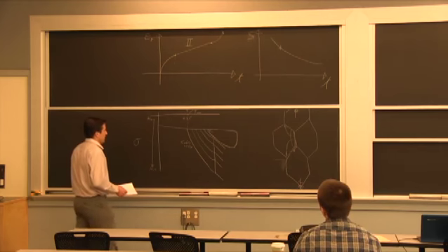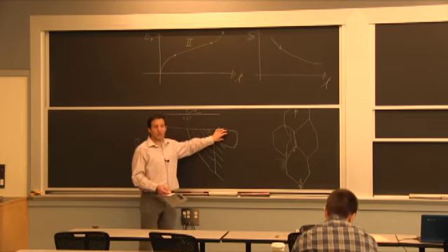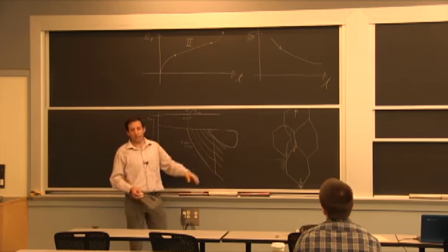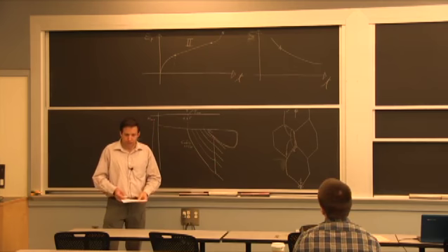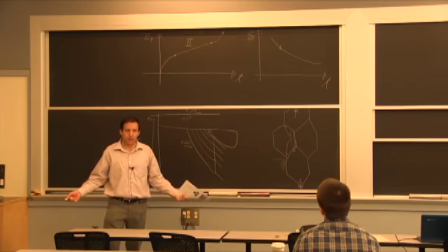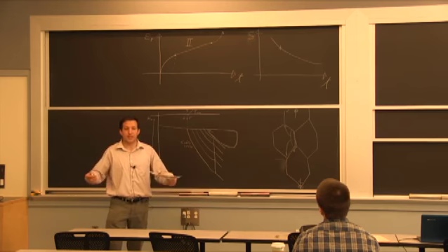At the limit, it's not that different from ambient temperature, it's just a different speed. At ambient temperature, when you deform a metal, you'll reach a point where you have so many dislocations that you don't have hardening anymore. It will take a long time. It may be 200–300% strain before you reach that steady state region.